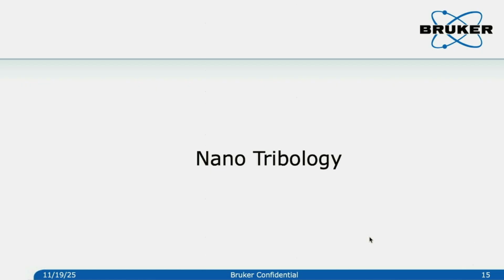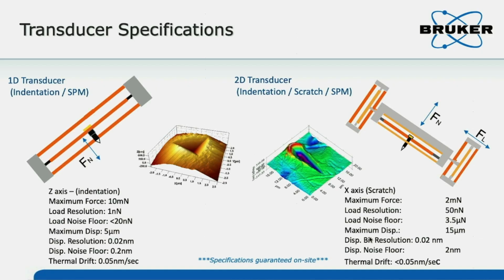But we also have the nano tribology test. So this is the transducer technology we call a capacitance transducer. Normal indentation, we use the capacitance transducer to apply the static electrical force. So this transducer can output the nanoscale force and the displacement information to us. If we make the transducer this way, we have the force in the normal direction. We also can get the force in the horizontal direction, we call the lateral force. So this will output the two direction force and the displacement. This will allow us to do the tribology testing, we usually call the scratch. The tribology testing in the real micro and nano scale.